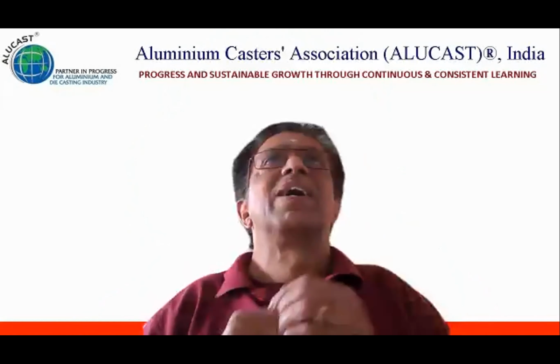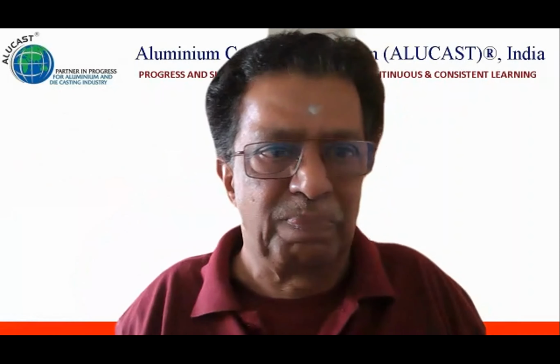The next question is from Mr. Sachin Kumbhar: what will be the effect of silicon being more than 12%? See, I touch this point again. If it is more than 12%, the alloy maker will find it difficult to dissolve it in the first place. Second, anything beyond the eutectic point of 11.7, silicon dissolves in the molten metal, but when you make ingots or a casting, the silicon comes back as a crystal form. These crystals form hard particles and your tool tip will get spoiled.